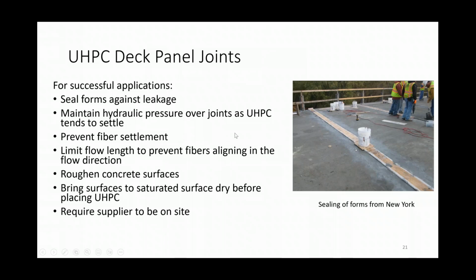The other key thing is that if you're pouring UHPC at point A and expect it to go to point B, and those two points are very far from each other, and UHPC is just going to flow a very far distance, then what people reported happening is the fibers essentially all orienting in the direction of the flow, which is very undesirable. So we do want a random distribution of fibers. So keeping those flow lengths short is recommended.